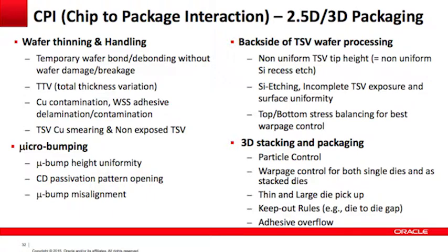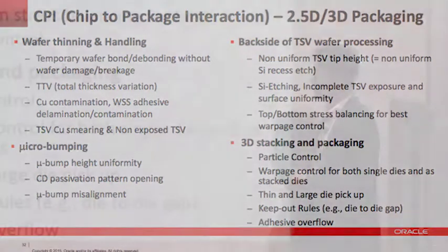3D stacking challenges. One area is particles. I work with a lot of manufacturing sites like TSMC, wafer fab, and other assembly, and particle is always the troublemaker. When they have a Pareto breakdown of the top 5 defects, I recommend: you control particles, then your order of the Pareto is going to shift. So this is always a troublemaker. And the second one is warpage, and then other handling processes are challenges.